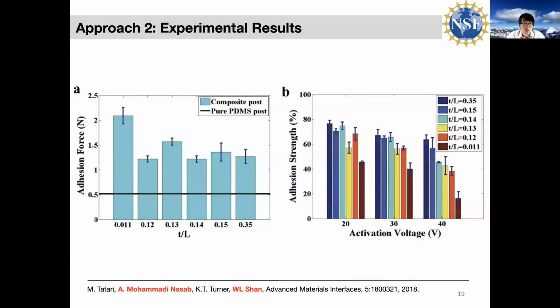You can see that these are experimental results. The dry adhesion of the composite post is higher than that of the pure PDMS post. And when you activate the sample using voltage, either 20 volts, 30 volts, or 40 volts, you can see different levels of dry adhesion tuning.